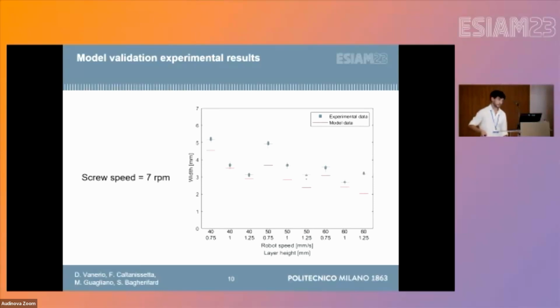We have just one value in this data set which lies outside of what we expected, the one in the case of 60 millimeters per second, 1.25 millimeters layer height. But this is a very extreme condition, a limit condition for the manufacturing, so this could be the cause. Nevertheless, the model data, which are the red ones, always underestimate the experimental data. The same is true also for the other screw speeds.